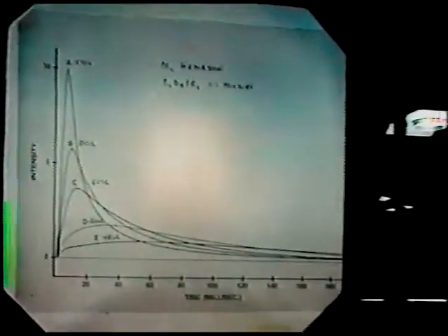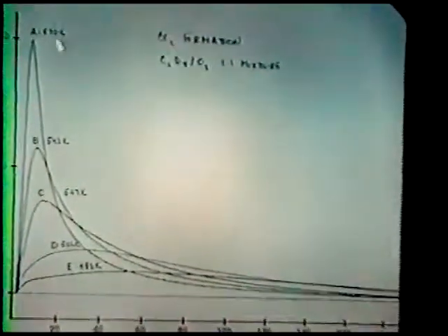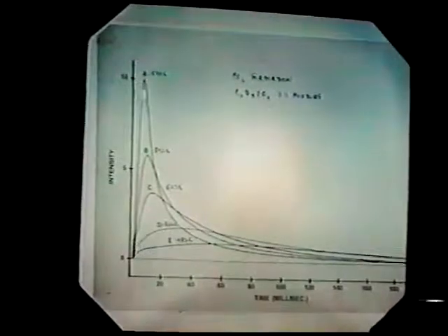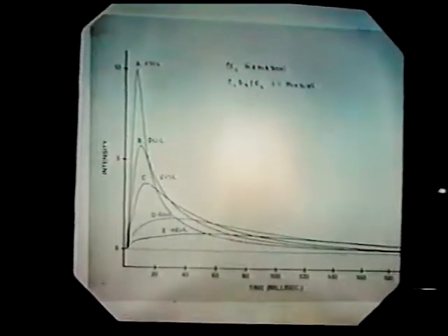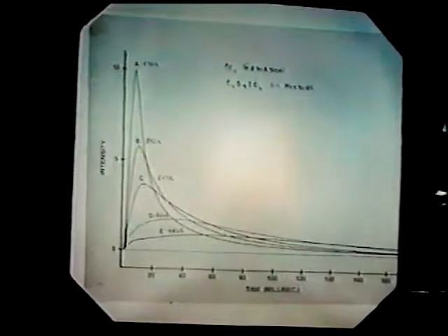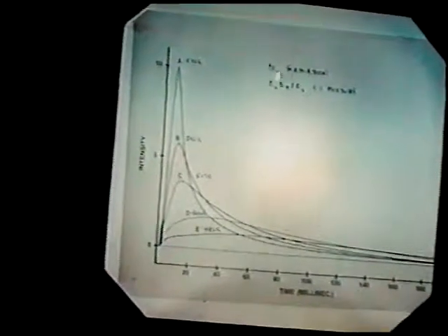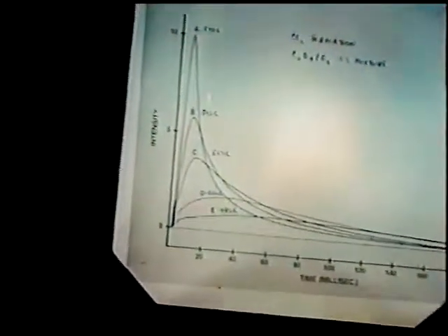Here I show a number of TAP curves for the CO2 formation, again a 1-to-1 mixture, varying the temperature of the catalyst. And again you see that the amount changes, although it's very difficult in these experiments, because of the breadth of some of these distributions, to integrate this very accurately. What I want to show you here is how the tail, the characteristic time for the formation of this product, the CO2 product, changes with temperature.